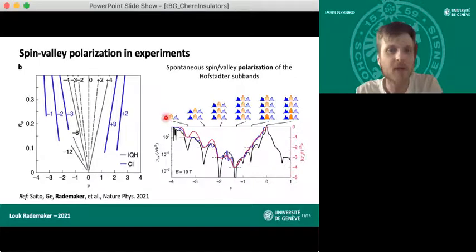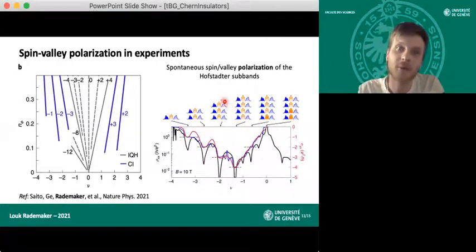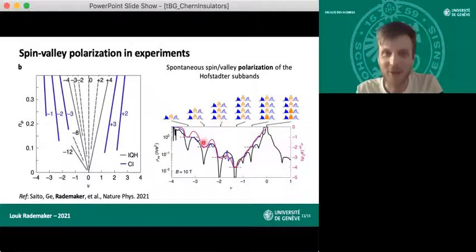where we just expect that this blue band of the Hofstadter is only occupied with 1 flavor. And then you get a -2 state where it's occupied by 2 flavors. And there's the -3 state where it's occupied by 3 flavors, and so forth. After the -4, it goes back to 0 because you start to occupy this +2 Chern band, the 0th Landau level, and that compensates and brings the state back to a 0 Chern number insulating state.